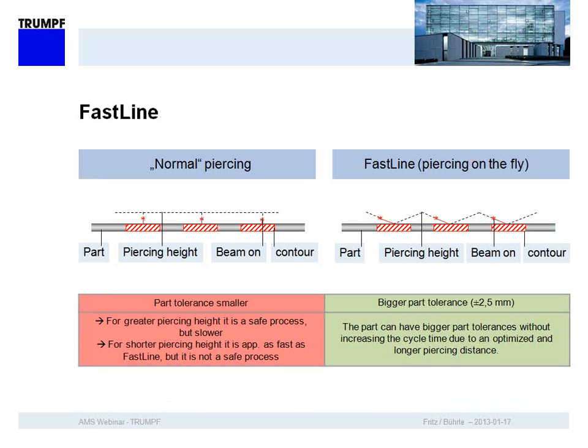When I come to a function of the machine, which is called fast line, this is a function that allows the piercing on the fly. At the end, what it does, it reduces the cycle time. When you look at the left picture here, that's the normal sequence of piercing. So the laser head would come to a pierced position. This is a hole cut into the sheet. Then you ignite the laser, you start cutting the hole, and you go up and go to the next hole.